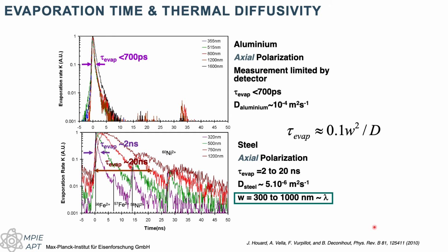Again, I invite you to read some of those papers, but this also then depends on the heat conductivity of the material. So for example, for aluminium that conducts heat very quickly, the difference as a function of the wavelength is not that bad, because even if the absorption is down the shank, the heat will travel fast to the tip and then back.